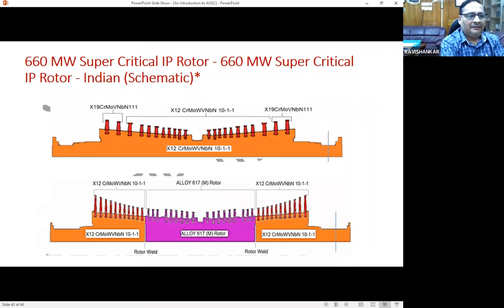turbine rotor, sir. So the intermediate pressure basic construction for a supercritical is we have got that X12 CrMo material and the X19 material, that's the blades. First of all, what we did was, sir, the total rotor was conceived with alloy 617 forgings. It proved to be a very costly affair. Then rethinking was done, and we went to a very novel concept of a welded or bimetallic rotor, wherein the high temperature zone alone, when the temperature was beyond the limit of X12 material, the alloy 617 was used, and at both ends we had gone with the regular material of construction.